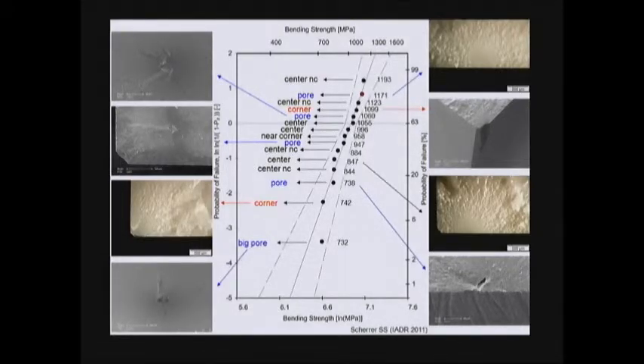Well, there was a major processing pore in volume. And then all of a sudden you see that your population of defects, it's either grinding or processing. Sometimes it's a corner crack. Sometimes it's a pore at the surface. Sometimes it's a grinding thing. You need to understand the failure specifically in ceramics.